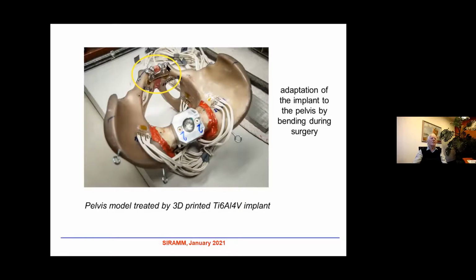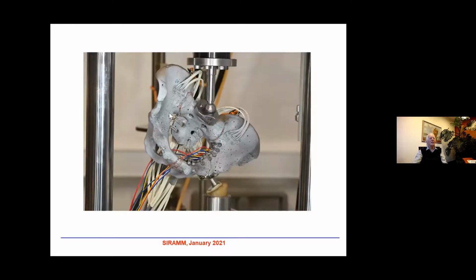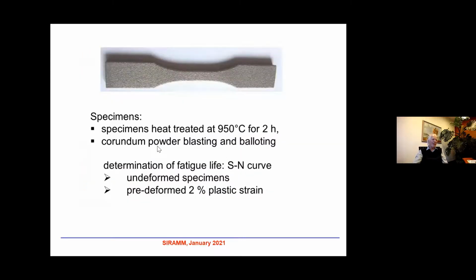It is here, the symphysis region, and we have cycled this pelvis treated with this implant in a cyclic machine, and we observed how this implant behaves. We have also prepared specimens for tensile tests, and these specimens were heat treated at 950 for 2 hours, and the surface was treated by corundum powder blasting and balloting. It is the same as is used for these implants.